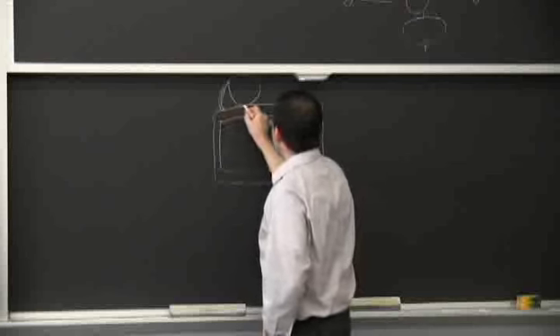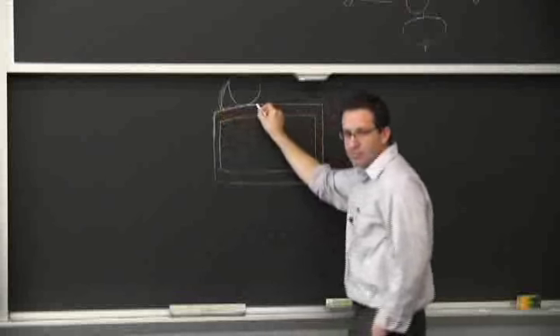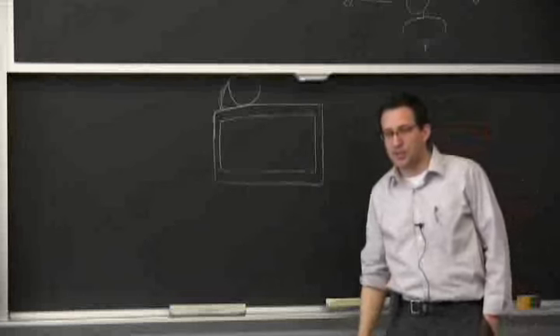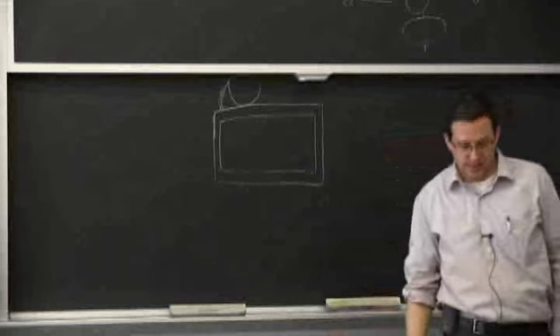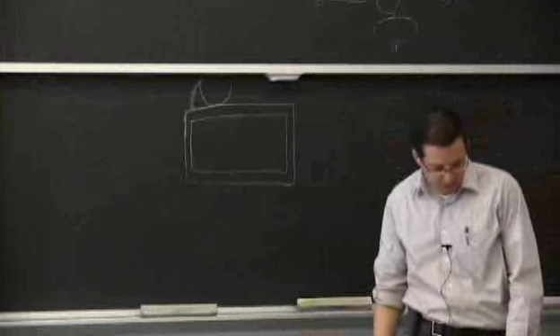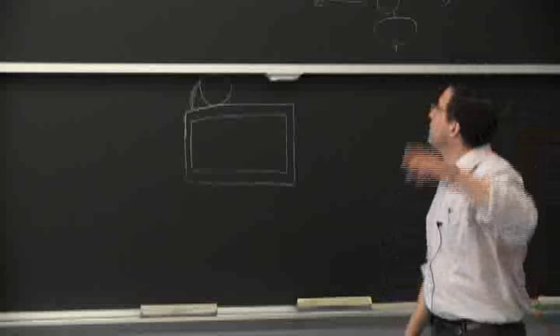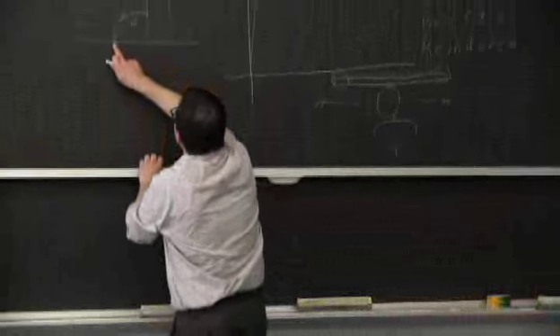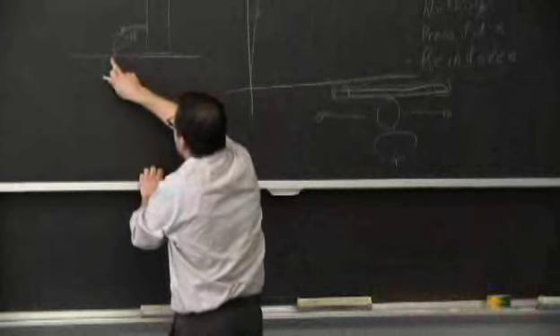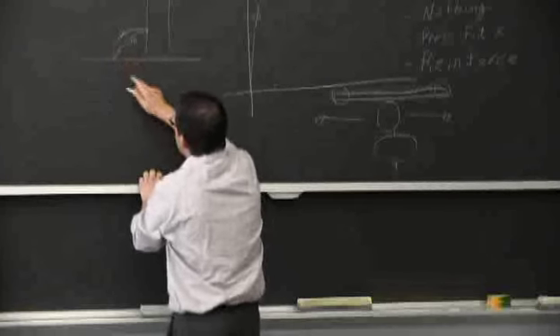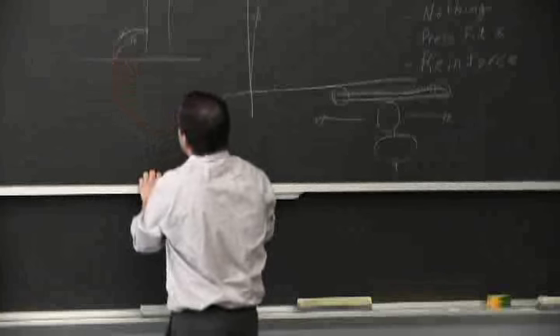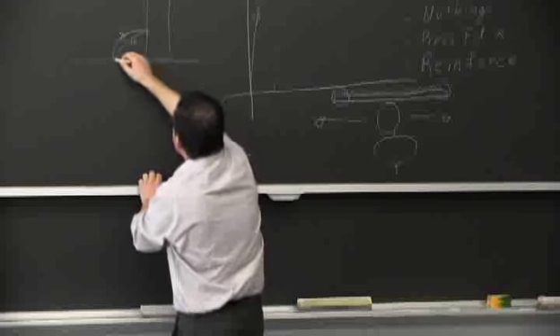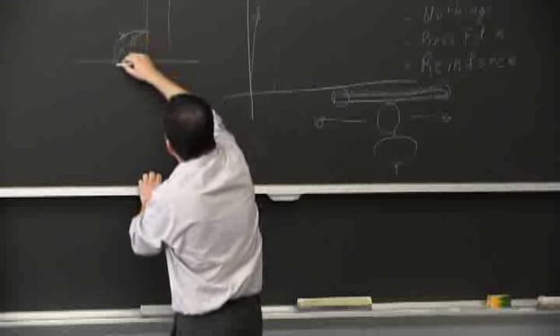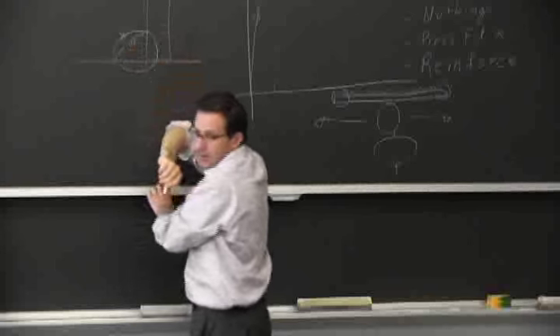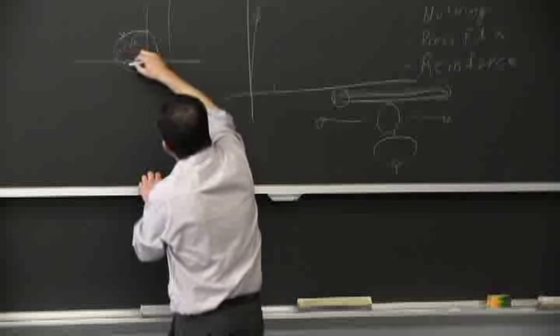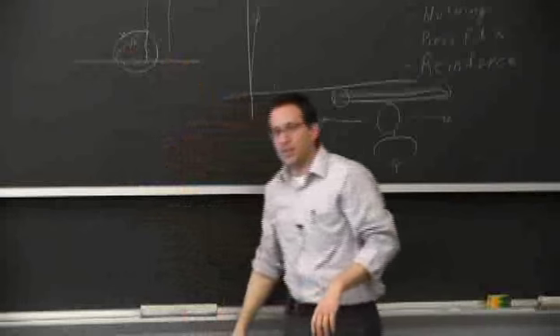And after the fact, what we find is we still have that very shape of the exterior of the rectangle, so it means no fusion. And it's not completely uncommon. It's related to having this convex bead shape that we talked about here. So somehow I end up almost perpendicular here, and there are different criteria. There's an ISO standard to describe how big of an angle you're willing to have. So instead of having a bead that will look like this, if you look under the microscope, it'd be some kind of shape just filling the gap, essentially.